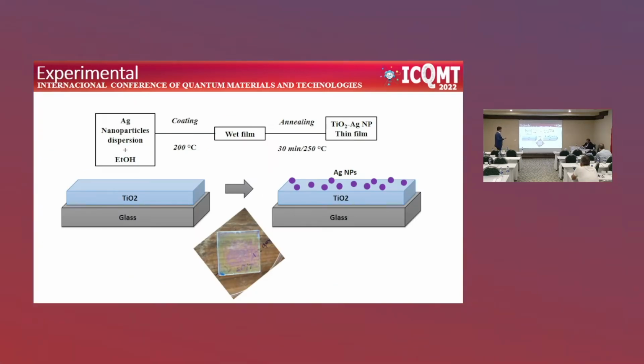Well, when we have this dispersion, we apply it onto the surface of the titanium oxide, and then we anneal at a lower temperature compared with the titanium oxide. Why do we use this temperature? In order to try to attach the nanoparticles on the surface of the titanium oxide. Then we do a post-annealing at 250 degrees in order to obtain this heterojunction between the titanium oxide and the silver nanoparticles.